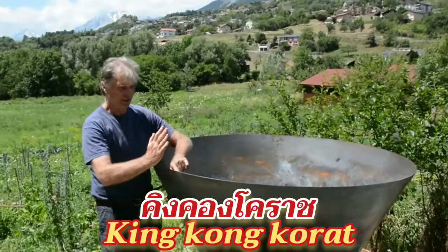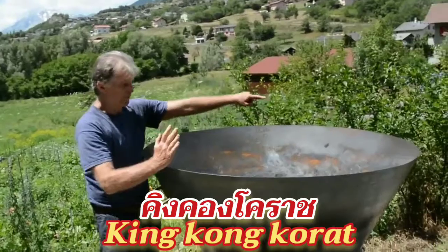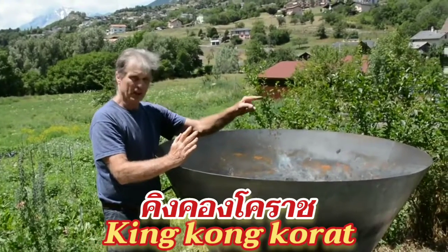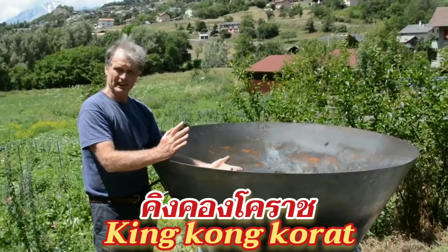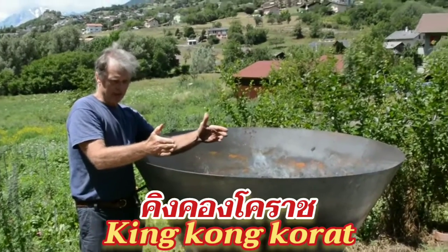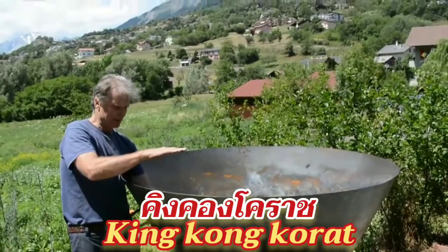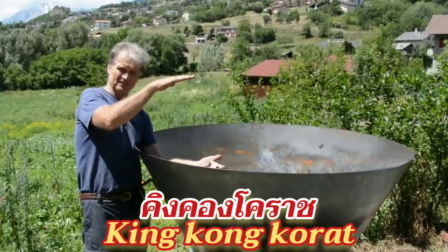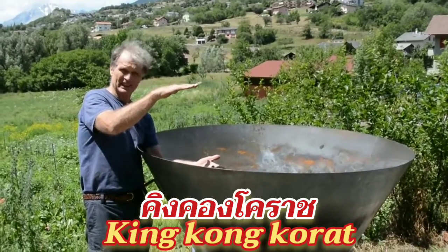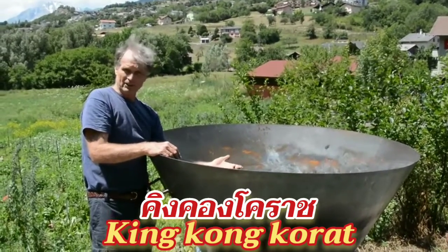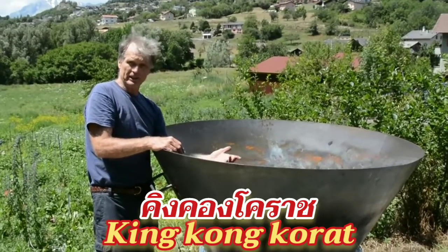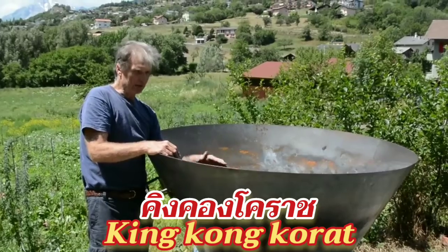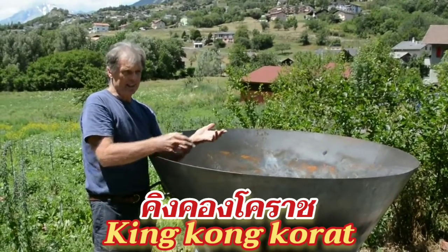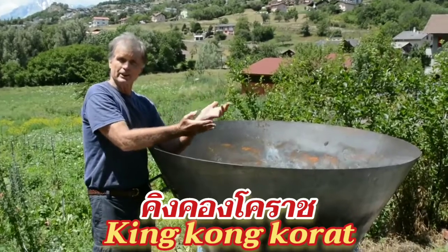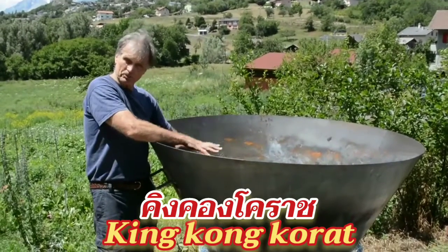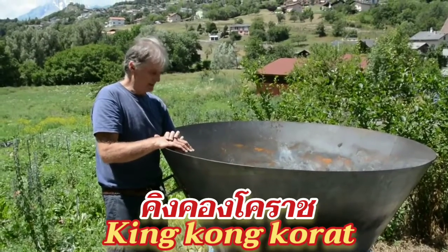So you end up with a loop in here like this. So this updraft creates a loop, a toroidal vortex all the way around the cone, which feeds oxygen in and down into the material in the cone. The vortex may vary in size, but it's something like about this size. So it penetrates about so far down into the kiln, 50, 60 centimeters, and the material at that level, the char, can in fact begin to oxidize and turn to ash. So as that happens, we layer another layer of wood on, and the flames and the updraft from that layer of wood keep the oxygen away from the layer below, and it just keeps all settling down into the base of the kiln, the biochar that's created.